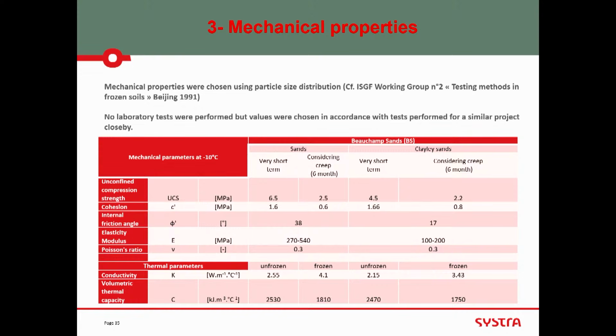Now we are going back to what we have seen. It creeps a lot. When you do a UCS test, very short term, you get 6 MPa for the sand when it's frozen. Design value is 2 MPa, 2.5 MPa. For clay sand, the strength is less, as we saw before. It's 4.5 MPa. We take 2.2 MPa when we take the creep phenomena into consideration. Modulus is about 100 UCS, and a little less, 50 UCS, when it's clay.